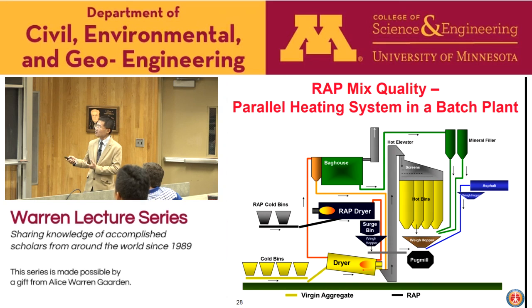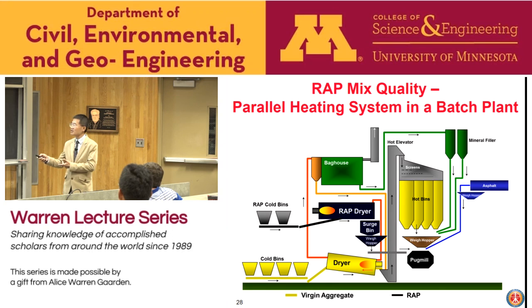Then the RAP material will drop into the surge bin here, where a rejuvenator will be mixed with the RAP material, giving time to activate and condition the RAP material in the surge bin. After that, the RAP material will be put into the pugmill to mix with the virgin aggregate coming from this direction and virgin asphalt coming from this direction. Using a separate dryer allows asphalt mixtures with a high RAP content. That's the basic concept here: because we have a separate dryer, we can use more RAP in the asphalt mixtures.